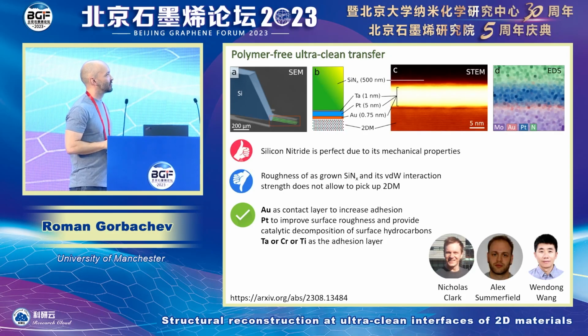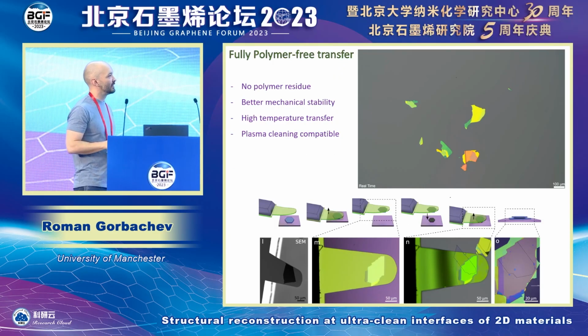And silicon nitride is extremely high temperature stable. You can put it in ultra high vacuum. You can put it in all kinds of corrosive liquids to clean your samples. And it is more mechanically stable. And so the idea is really simple. For research, for small structures, we use this cantilever shape, which is similar to an AFM style cantilever, only it's a lot wider and a lot longer.